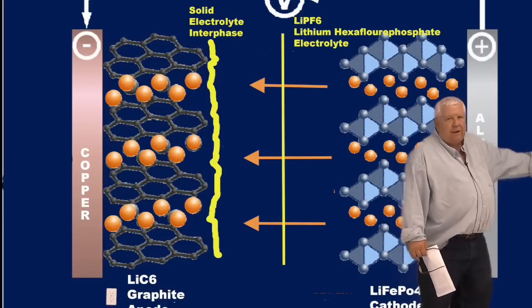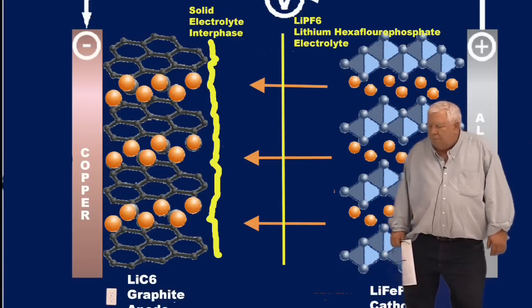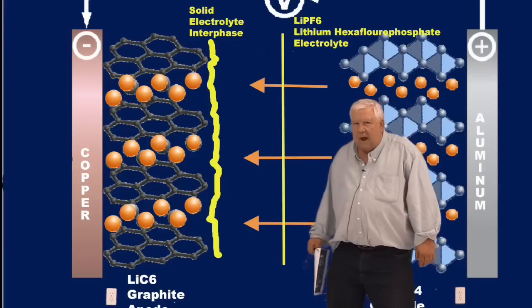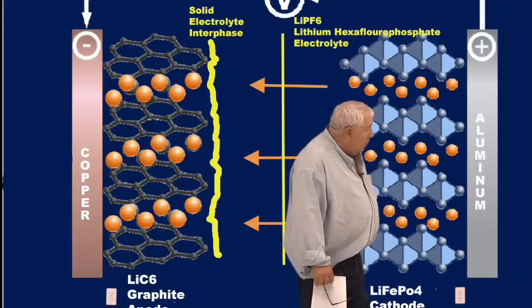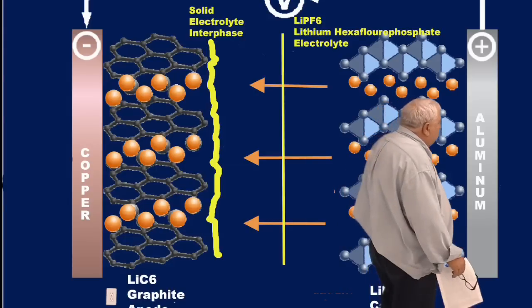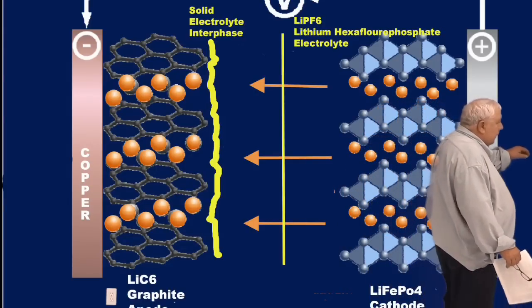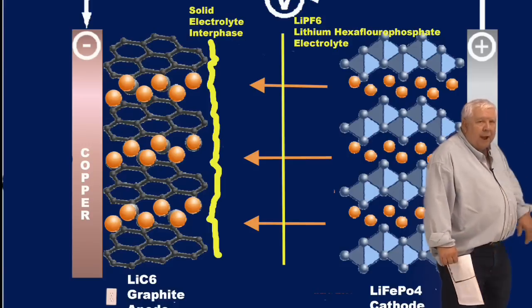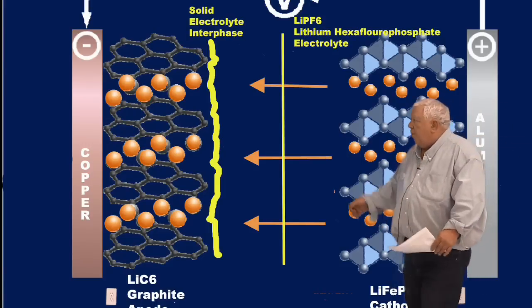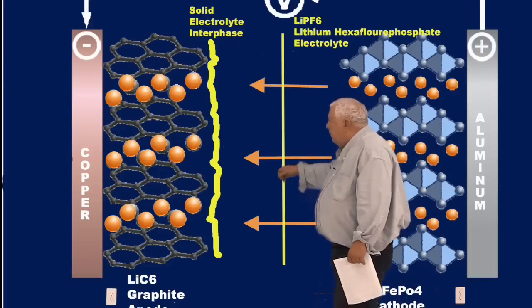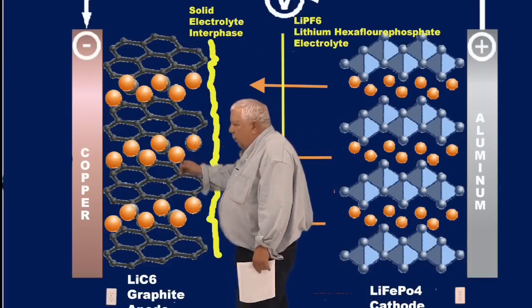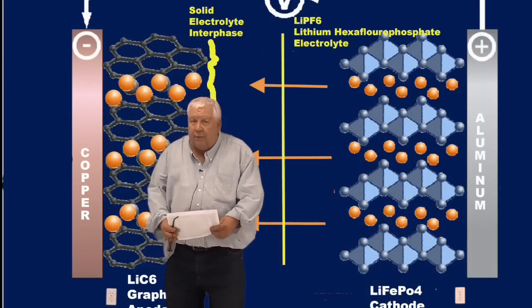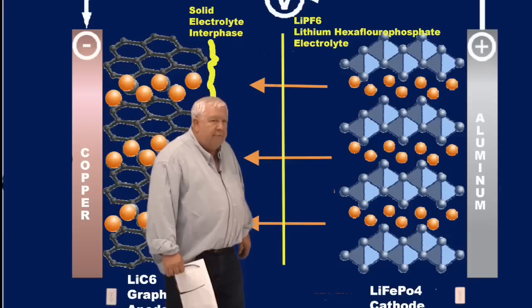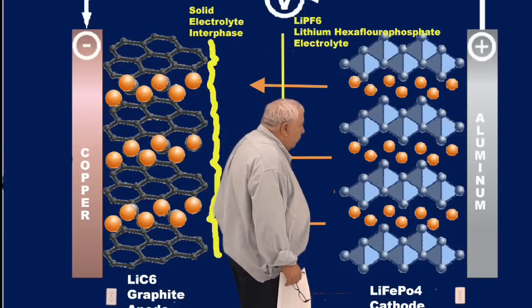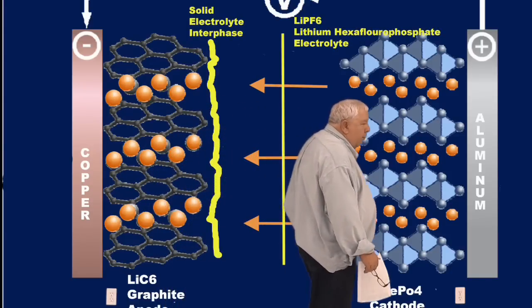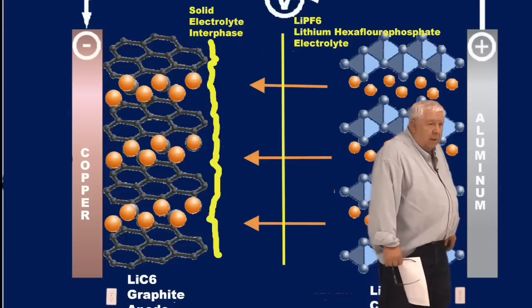It's a much safer chemistry than lithium cobalt or lithium manganese oxides, which readily give up oxygen. You've got to heat this up to twice the temperature to get it to do it. Once that oxygen starts to come out, now we're feeding the whole thing. The oxygen starts to react with the electrolytes and with the rest of it, and the result can be an extremely hot fire, and we've seen the results of cars burning to the ground, primarily from overcharging.